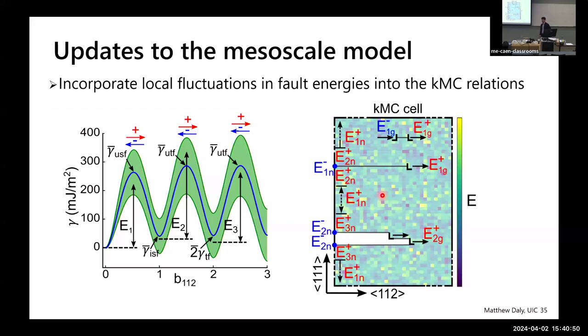And what we're doing, instead of just dealing with these static barriers that are updating with and tracking the deformation history of this crystal, is we're now injecting statistical information here. So the barriers now have some meaningful statistics that are mapped to what we measured in molecular statics simulation. So you can imagine that not only is the barrier being updated for some deformation process with respect to its plasticity history, it's also being updated with respect to the solute statistics that we've grabbed from molecular dynamics or molecular statics simulations.